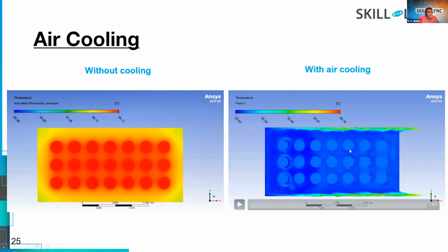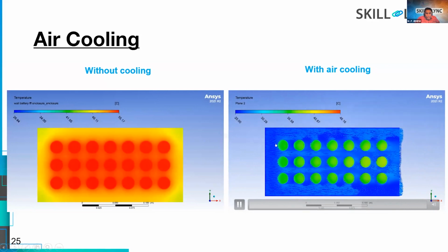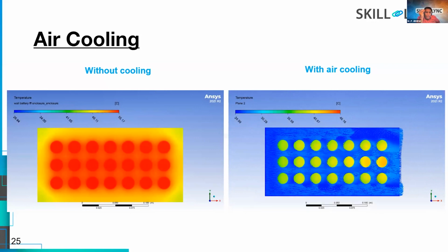I'm just sending the air from the left hand side to the right hand side with a velocity of 5 meters per second. So what happens here? Even though the temperature of the battery increases, it is limited to 46 degrees Celsius. With a velocity of 5 meters per second, I am able to maintain a temperature of 46. So the difference is 55 minus 46, almost 9 degrees Celsius. So by changing the velocity, changing the spacing between the fluids, or using different flow mechanisms, you can study the temperature distribution of the battery pack systems.